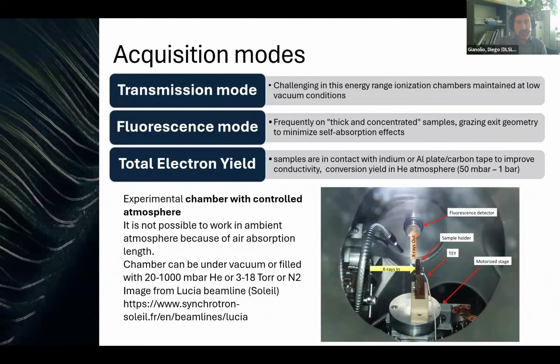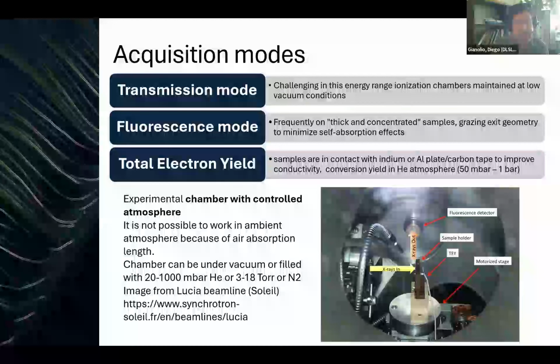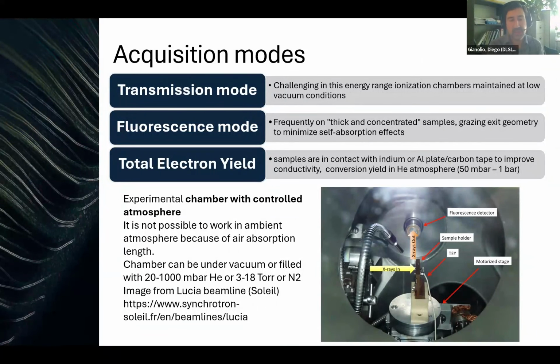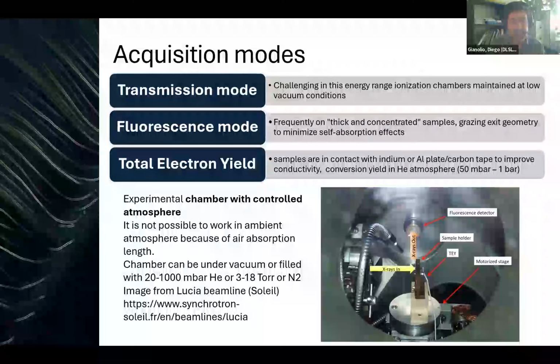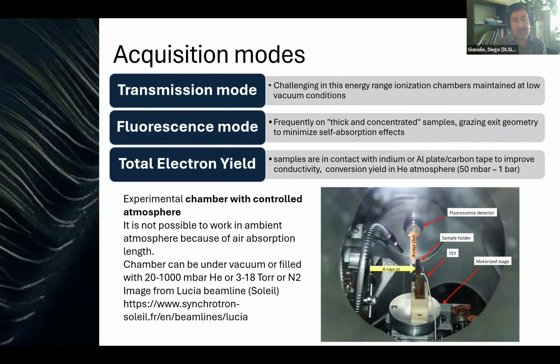And in terms of data acquisition, most of the tender X-ray beamlines will have an experimental chamber where the sample is measured in controlled atmosphere. This is due to the fact that, as we said before, it is very hard to measure in air due to the air absorption. So we cannot work in ambient atmosphere. We need an experimental chamber.